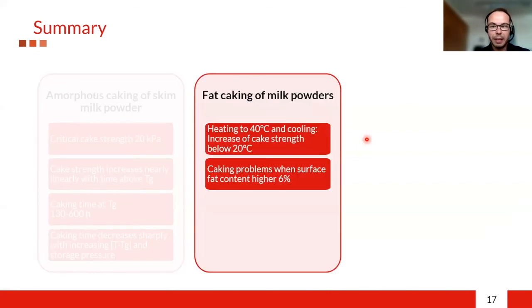For the fat caking of milk powders, the heating to 40 degrees Celsius and the cooling affects the cake strength below 20 degrees Celsius. So the cake strength increased below this temperature due to fat crystallization. Caking problems can be expected when the surface fat content is higher than 6%.